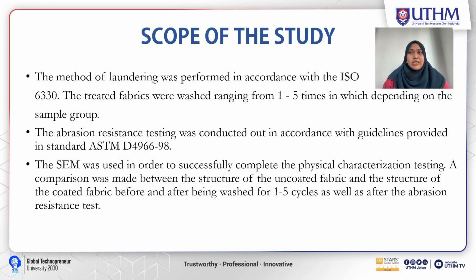Next, the method of laundering was performed in accordance with ISO 6330. The treated fabrics were washed ranging from 1 to 5 times, depending on the sample group. Okay, the abrasion resistance testing was conducted in accordance with the guidelines provided in standard ASTM D4966/98. The SEM was used in order to successfully complete the physical characterization testing.